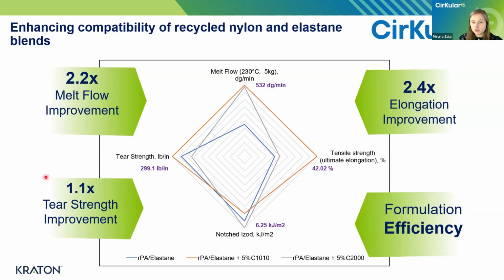By adding 5% Circular Plus C1010, what we've observed was really fantastic in terms of the mechanical properties. So we've seen 1.1 times improvement in tear strength, a 2.2 times melt flow improvement, thus enhancing the processability. And then lastly, we have also seen a 2.4 times elongation improvement, basically contributing to flexibility and durability. And you see here, I'm also mentioning formulation efficiency, which is basically about the fact that being such a low additive loading, it's a very cost efficient approach.